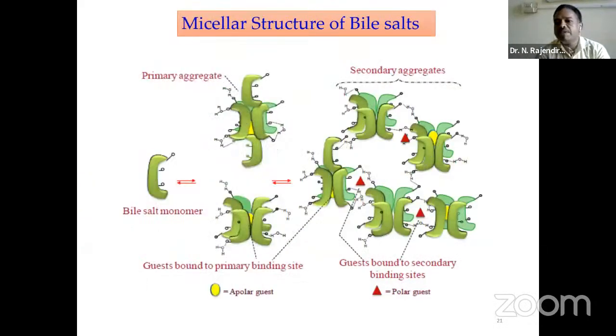Because of this reason, we use the bile salts as a stabilizing as well as a reducing agent. In the bile acids, the structure is shown here. Depending on the OH groups, they can be classified as cholic acid, lithocholic acid, and deoxycholic acid. And here there are two domains: the hydrophobic as well as the hydrophilic region.